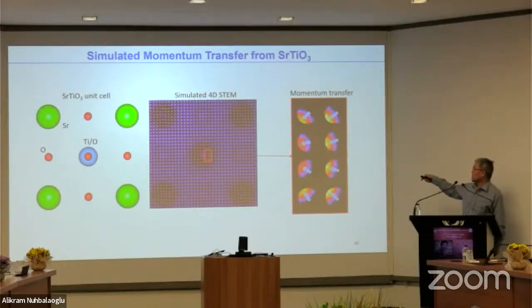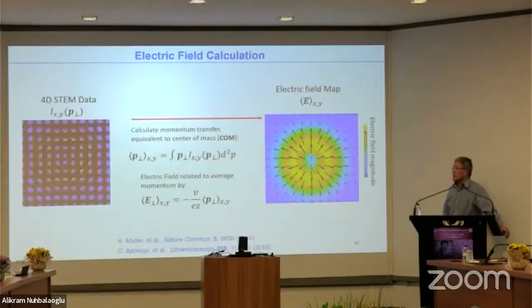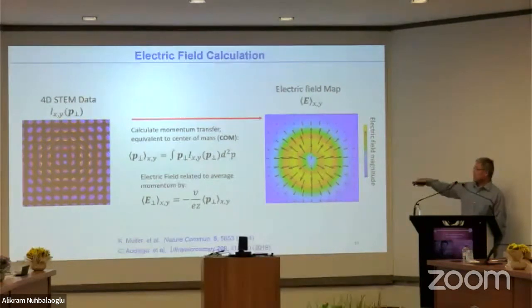So each point is a well-defined pattern. We call this a 4D scan because it is a two-dimensional scan, so you have 2D data, and at each scan point you have one diffraction pattern that is also 2D data. So the total is 4D; we call it a 4D stack. With the simulated diffraction pattern in 4D, you can calculate the field. The field is proportional to the momentum change, and momentum is determined by the center of mass displacement.